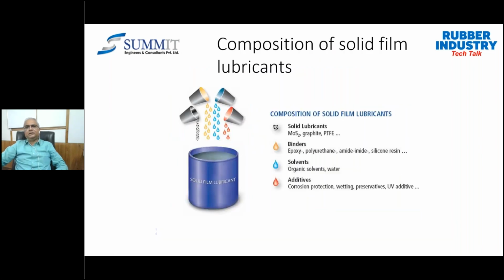I just mentioned that while making the composition of the dry film lubricants, the solid lubricants are mixed up with the binders, solvent, and the additives. Yes, these additives could be corrosion resistive or protective elements, or wetting elements, or preservatives, or ultraviolet additives, and many more. So depending upon the type of application, one will decide what type of additive is required. If you look into this combination, then it is very easy for you to define whether your process can be more sustainable or not.